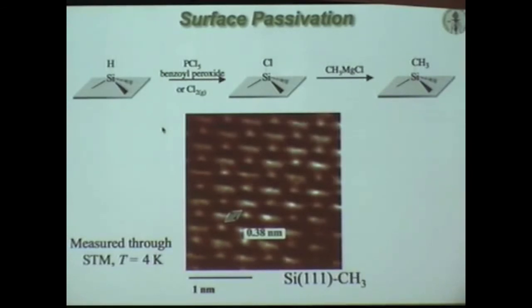By the way, I'm sure the Bell Labs people already know the other fact, that what we did is created all the surface area, and we should be killed by all the surface recombination at all that increased surface to volume ratio. But we have a way around that, because Yves Chabal at Bell Labs showed that you could hydrogen terminate silicon and passivate it, and the only problem with that is that it oxidizes in air, and the native oxide is defective because the silicon atoms in the bulk are sp3 hybridized, and they're bonded to all the other silicons, but not at the surface. And this is a strong bond, so it terminates that, except when it oxidizes, that creates traps.